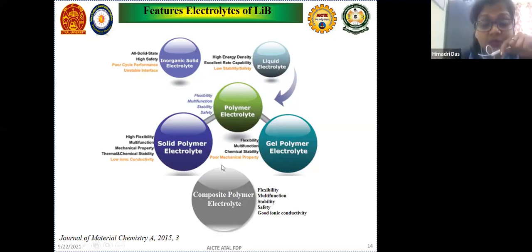So the next process thought of was implementing the synergetic effect of both solid electrolyte and gel electrolyte to make a quasi-solid electrolyte. This composite electrolyte is very good in flexibility, multifunctional stability, safety as well as ionic conductivity. But this composite electrolyte also has a problem in fabricating the devices, as well as long-term contact issues or resistance. They have a higher resistance. To avoid that, people are focusing on developing this electrolyte with different techniques, like mixing the electrolyte with the electrode material or increasing the conductivity. That is what can be really focused on for future research.